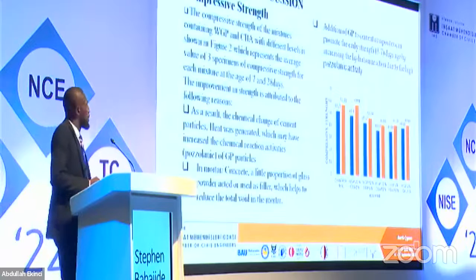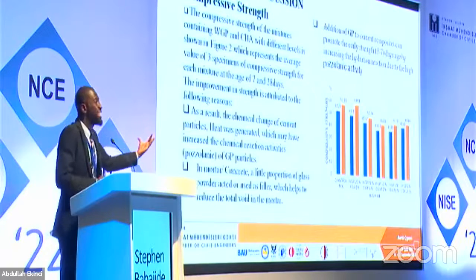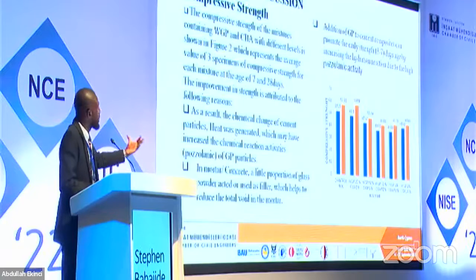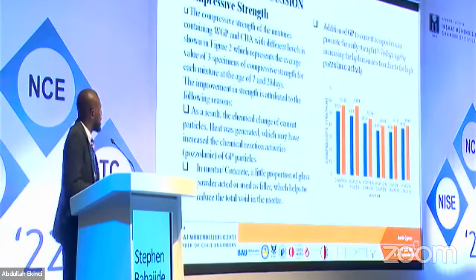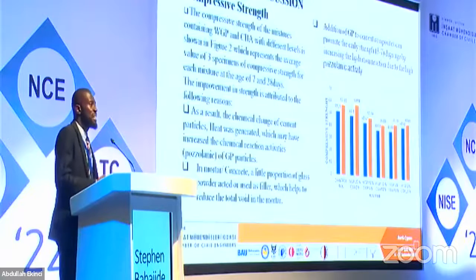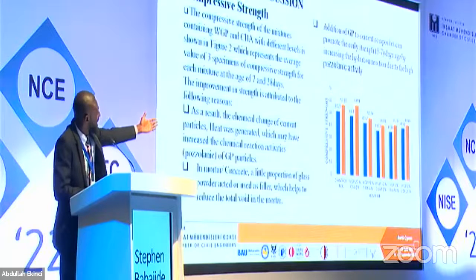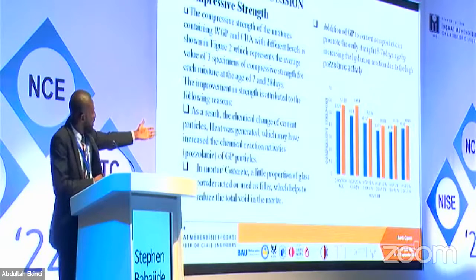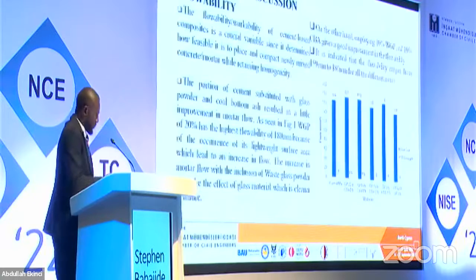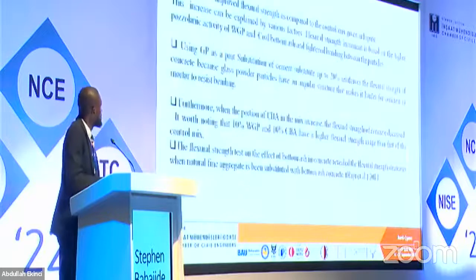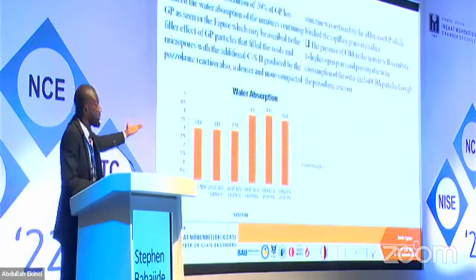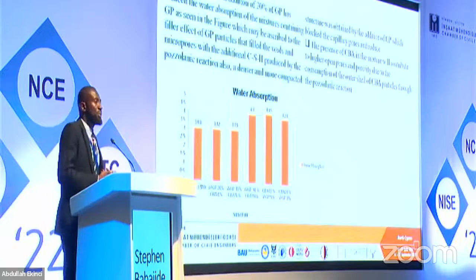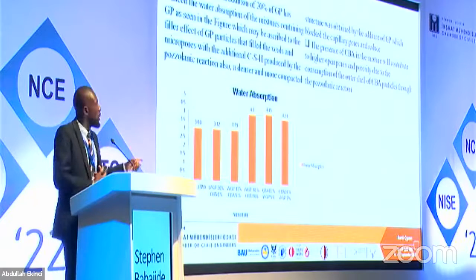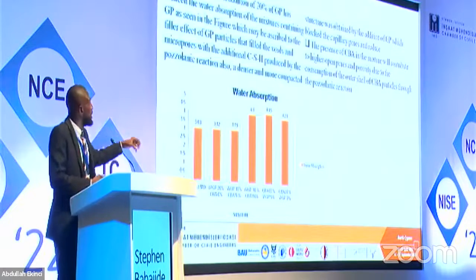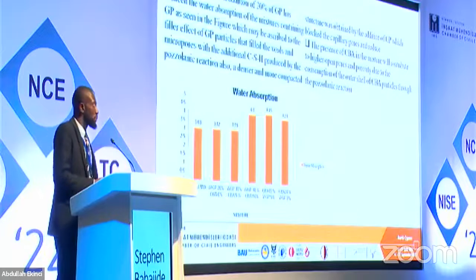Also, my compressive strength. My compressive strength has a higher increment with waste glass powder, and it increased in the early stage. While my CBA partially reduces, but at 28 days there's an increment. Those are my figures over there. I move to my durability test. Absorption of water. It is noted that 20% of CBA absorbs water, but 20% of waste glass powder reduces water absorption.